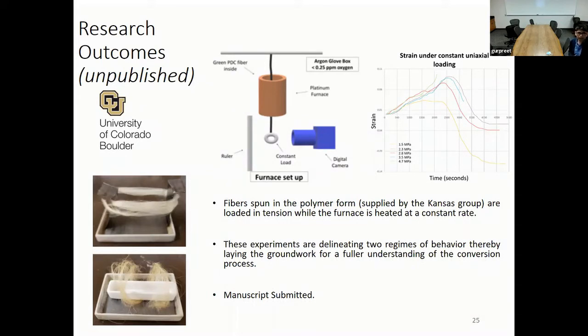So in this case, they utilized the hand-spun fibers that were prepared by my student, and they subjected those hand-spun fiber bundles to this kind of a test. And what you see here on this graph is that the y-axis is the strain, and the x-axis is the time. As you're heating the sample, you first observe a positive linear strain, a rise in strain as a function of temperature, so the sample expands. And then after a certain time, there is a switch. Now you have a negative strain and the sample shrinks.